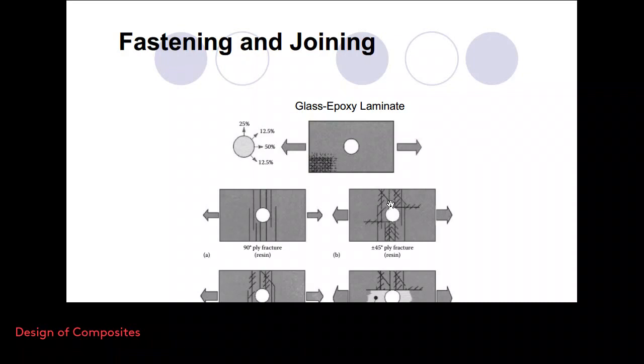What if we have 45 degree failure patterns? This means that the plies oriented at positive 45 and negative 45 degrees fail. We have a matrix failure in those plies. So we need to increase the number of those plies in that case. We may have 0 degree failure, in fact. So then, which means that we have lines in the direction of the force. So this figure is a little bit not correct, in fact.